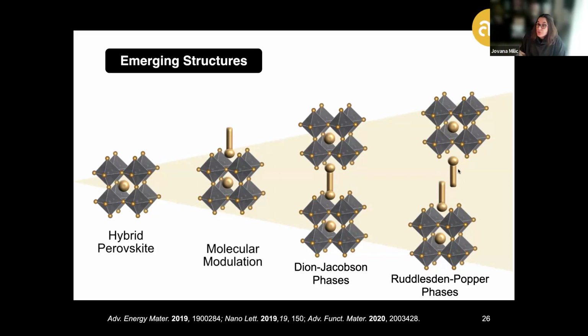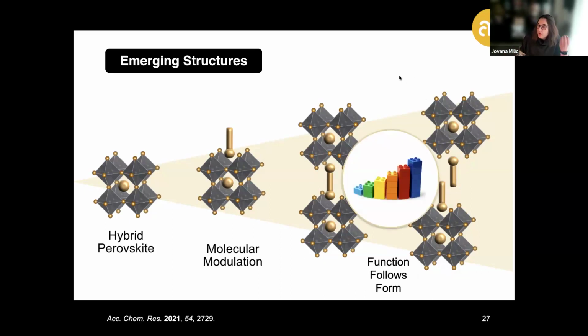In both cases, this contributes importantly to addressing one of the most pressing challenges—stability—through both the hydrophobicity of the organic component and its ion impermeability, while at the same time enabling these tailored systems to more directly contribute to the resulting properties of the materials through careful tailoring of the interactions between the organic components.